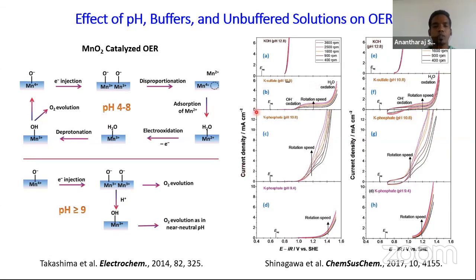And in this slide, let's move on to another area of neutral water splitting. I told you that unlike water splitting in acid and alkali, the water splitting activity depends largely on the pH of the solution, buffered and unbuffered solutions, and also the reactant available. So here is an example of MnO2 catalyzed OER. In the first step, we see an electron injection which forms Mn3 plus, which can undergo disproportionation to Mn4 plus and Mn2 plus, and this Mn2 plus has to be converted back to Mn3 plus, and this only can evolve oxygen. This happens in the pH range 4 to 8.